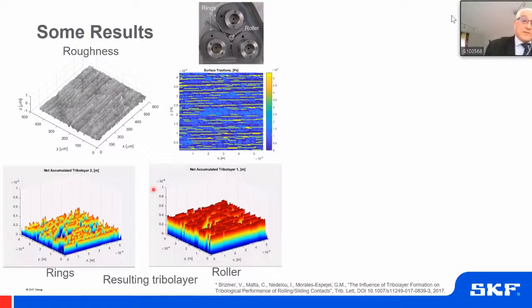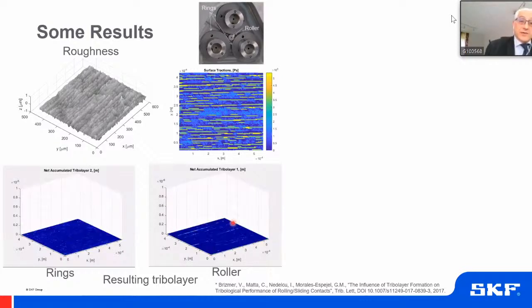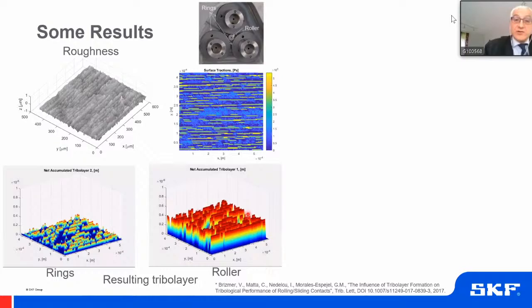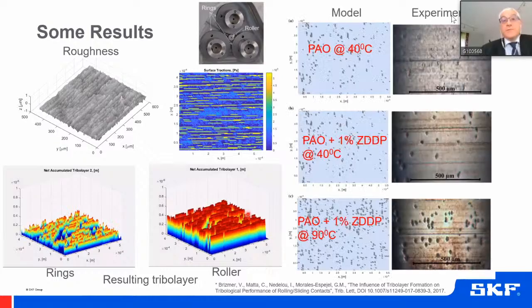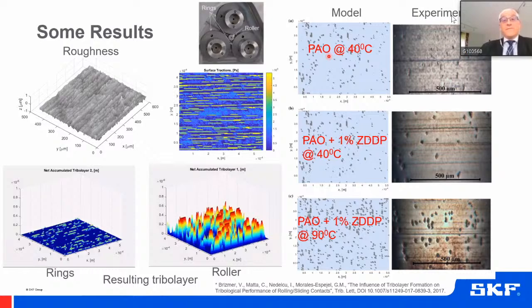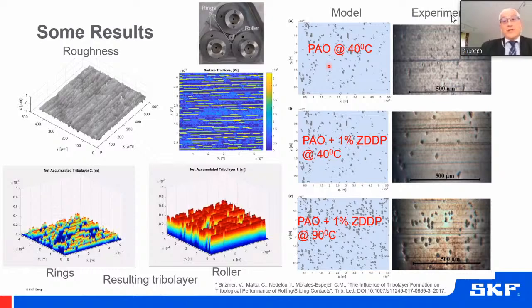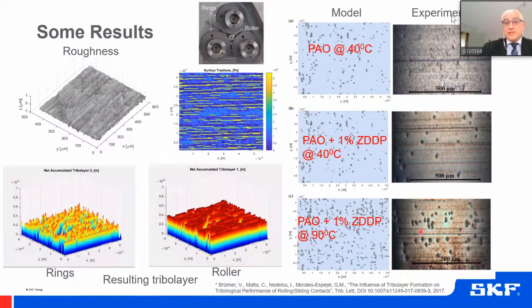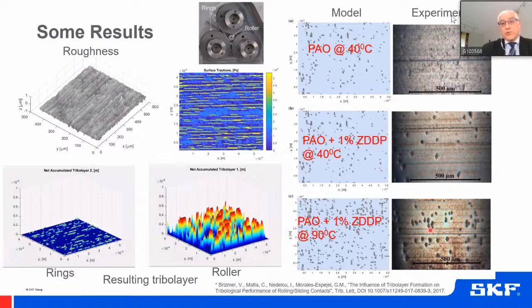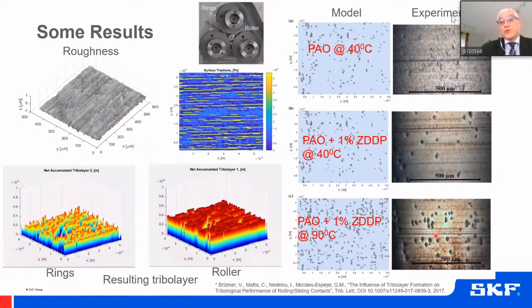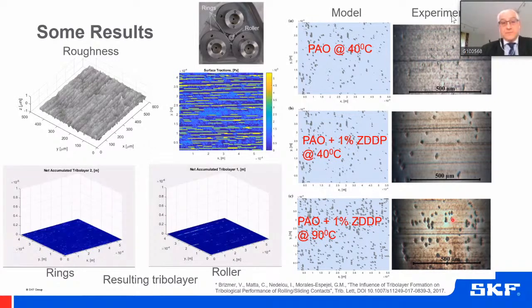But the important thing is not to stop here, but actually to try to make the link with performance. Because at the end of the day, this is what we are after. And for instance, it's interesting to simulate the same oil with a typical additive, ZDDP, but different temperatures. And then you have here the experiments. And we know that in higher temperatures, this additive is more reactive. So you will generate thicker tribofilms, which will prevent wear and will induce more easily surface fatigue. And this is what you see in the experiment.